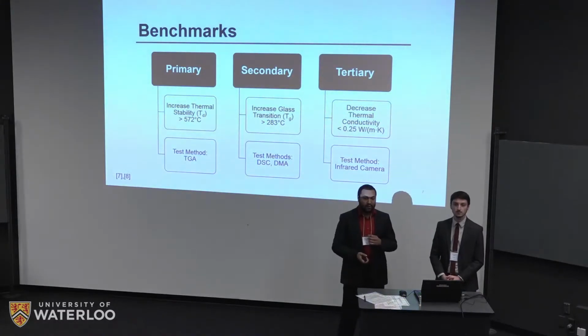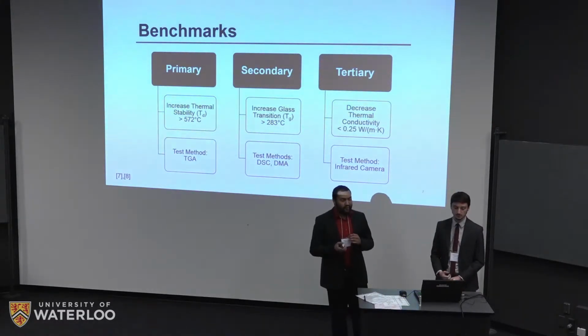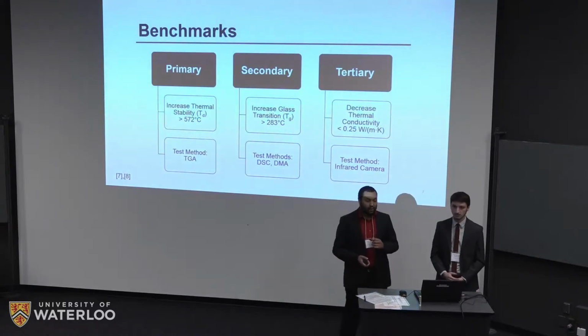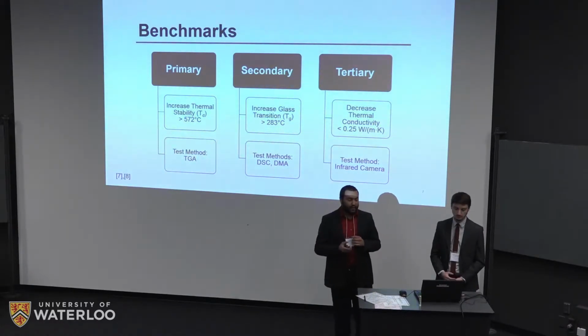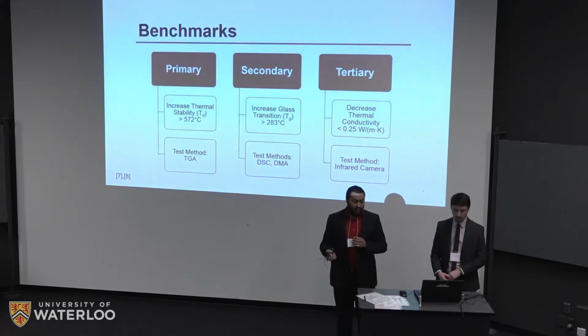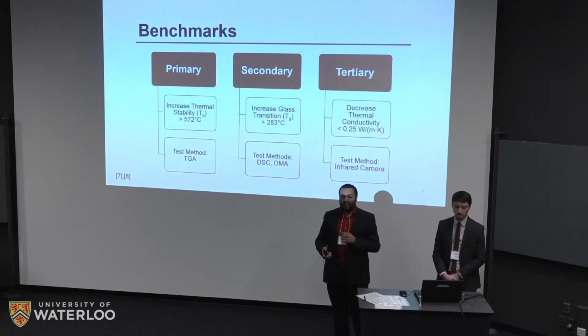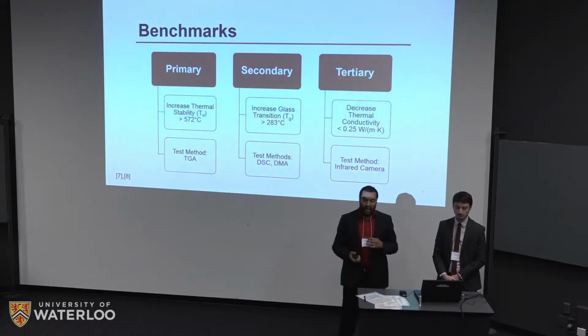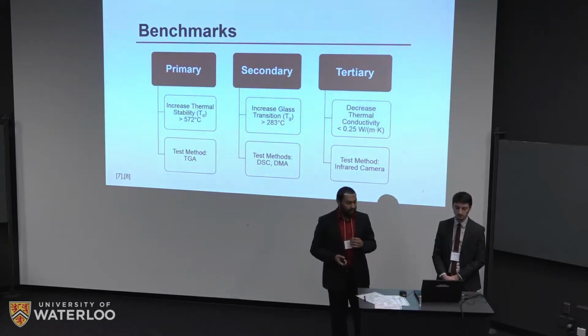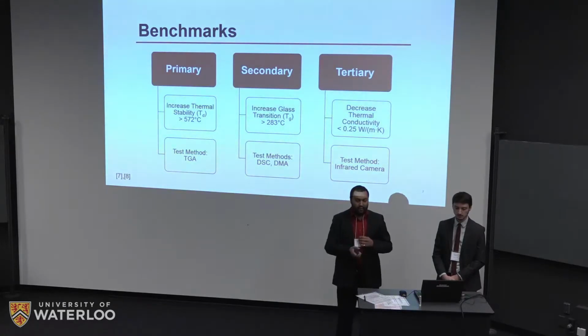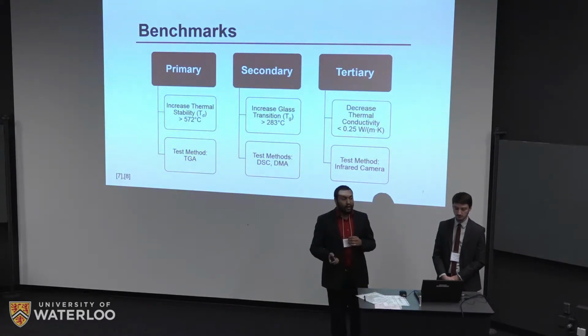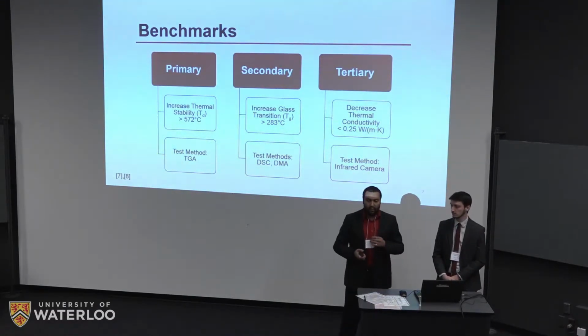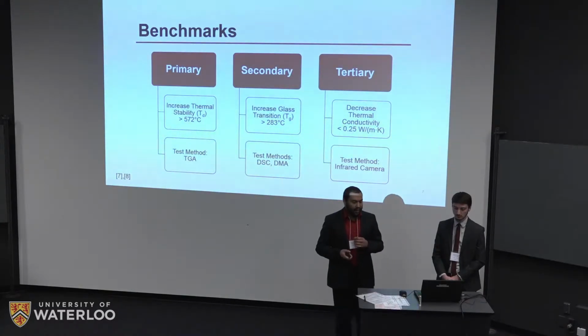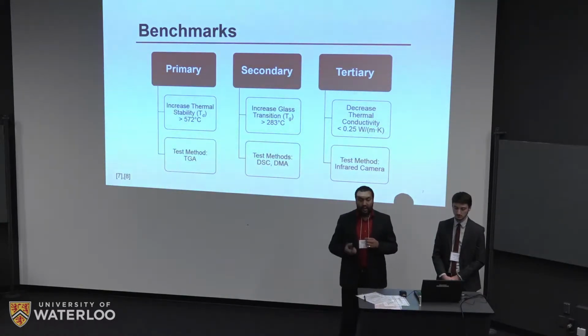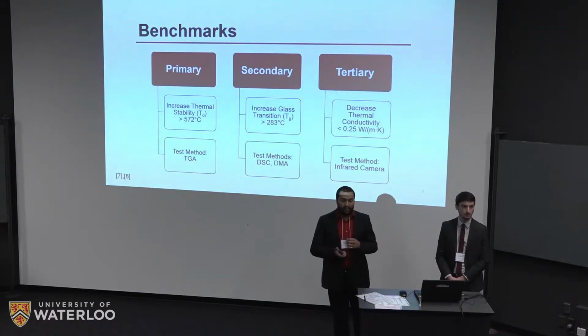So primary are some benchmarks. Primary benchmark is to increase the thermal stability. This is basically encompassed by the thermal degradation temperature. We want this to be at or above 572 degrees Celsius. And the secondary one is to increase the glass transition temperature. This is the mechanical stability or integrity of the polymer, of the material. And we want this to be above 283 degrees Celsius. These two numbers come from existing polymeric solutions in literature, and so we wanted to at least match them or beat them. And then our tertiary one is to decrease thermal conductivity. This number is actually taken directly from the Nomex data sheet.